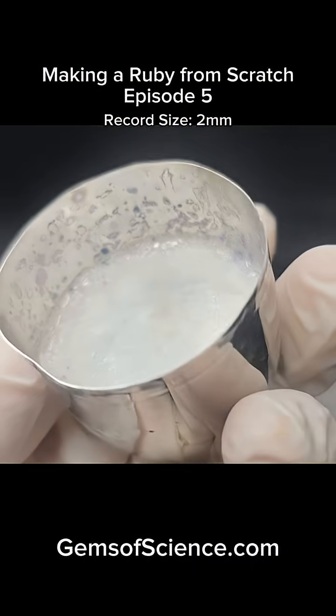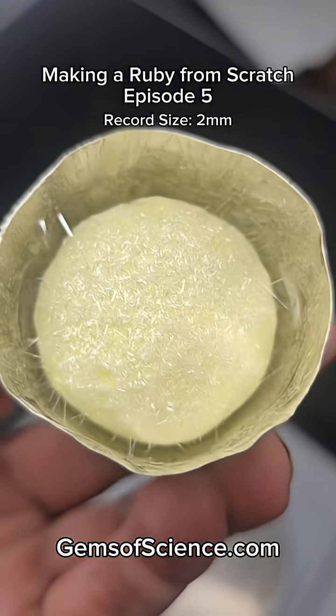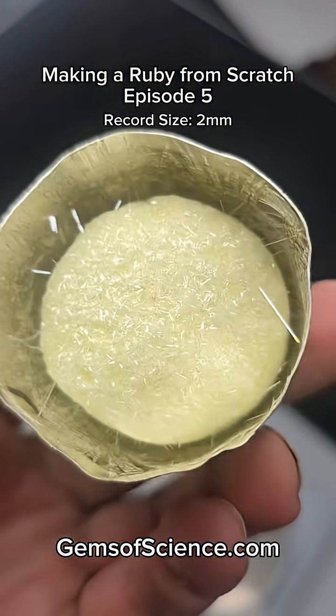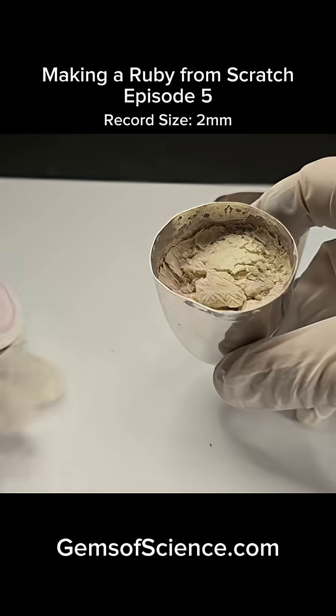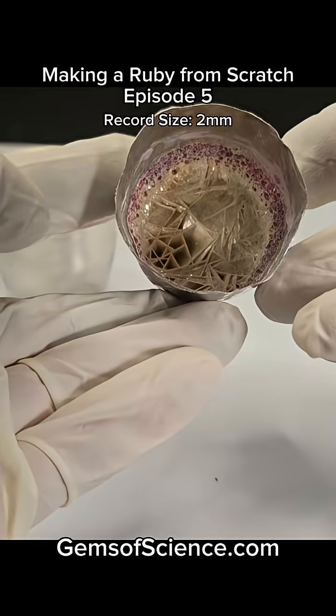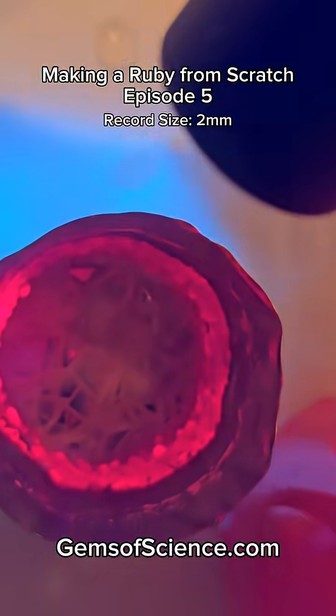The normal flux formed a nice flat sheet, but the lithium molybdate pulled together into a sparkly disco ball. Kinda weird. I'm also putting the max temperature higher since the crucibles can handle it. So let's see what we've got. The lithium molybdate didn't grow any rubies at all, but it also didn't evaporate off much, so it's still promising as a mixing ingredient. But the normal flux loved the higher temperatures my old crucibles couldn't handle.